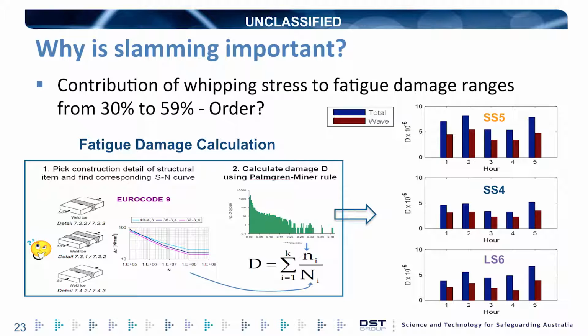And certainly for the Armidale class patrol boats, if they're doing a lot of slamming, this can reduce the fatigue life by about 30 to 60% compared to the ordinary wave loading. So again, Miner's rule is great, but the question is, what happens if I do this at the beginning of the life of the ship and not at the end of the life of the ship? What's the order of events? So what's the operational profile of the ship, and how does that impact the fatigue life? And again, there are no rules in the Eurocode 9 for bringing in the order of loading, and it's quite important for the fatigue life of ship structures.